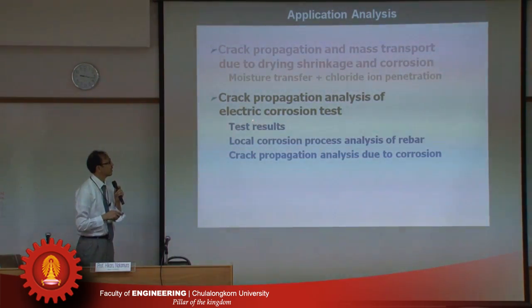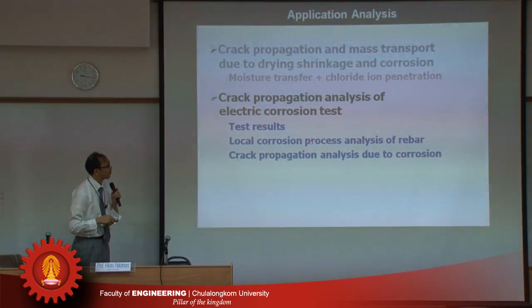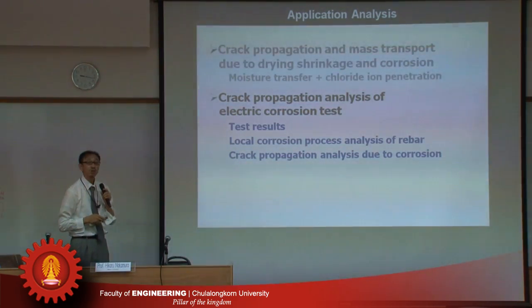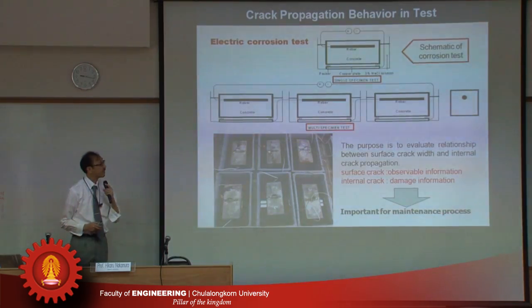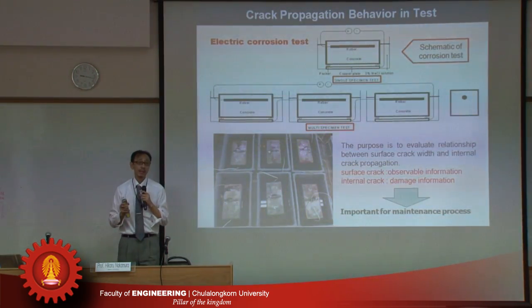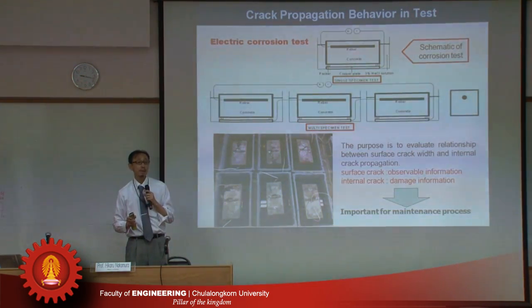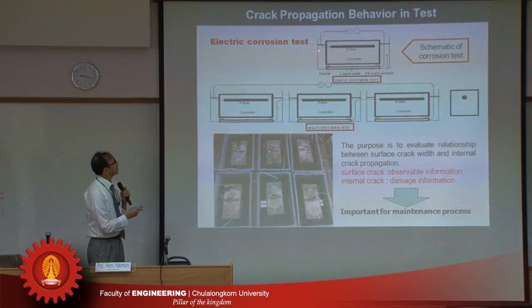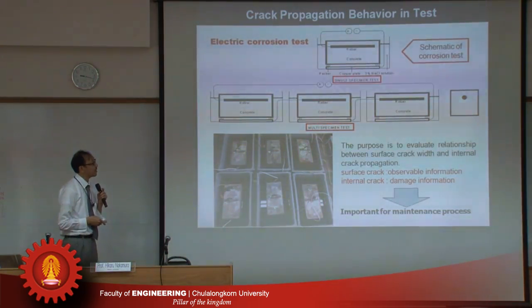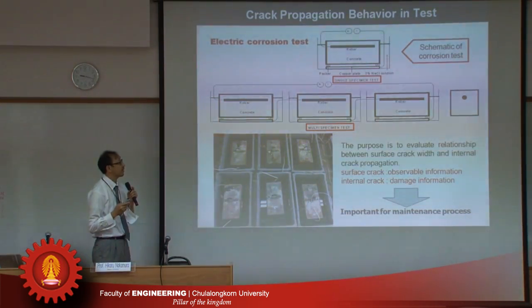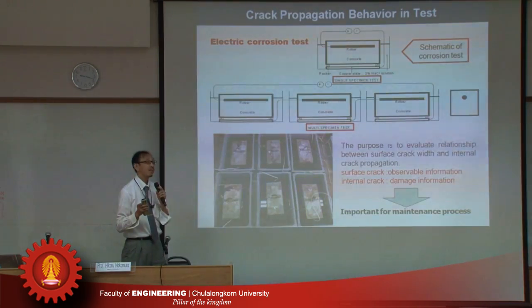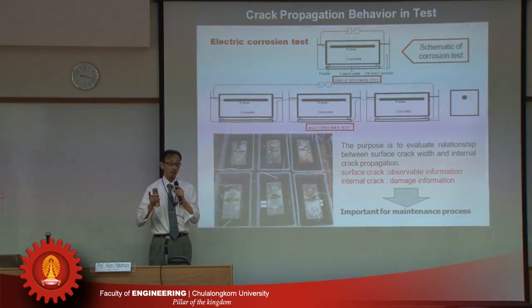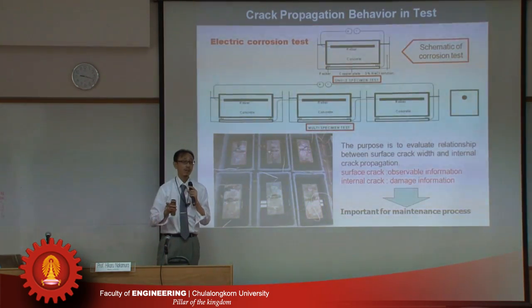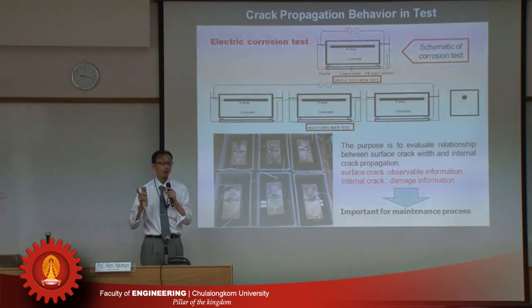So I chose the test result of the electric corrosion, and some analysis: local corrosion process analysis of the rebar and crack propagation analysis due to corrosion. First, please confirm the crack propagation behavior of the corroded specimen. A corrosion test was carried out like this. Many specimens were tested, and the purpose of this test is to evaluate the relationship between surface crack width and internal crack propagation, because when inspecting a concrete structure we can observe the surface crack. So the surface crack is very important, observable information.